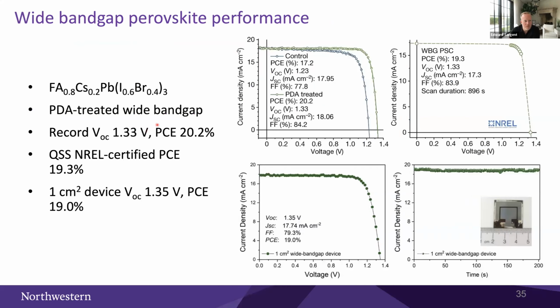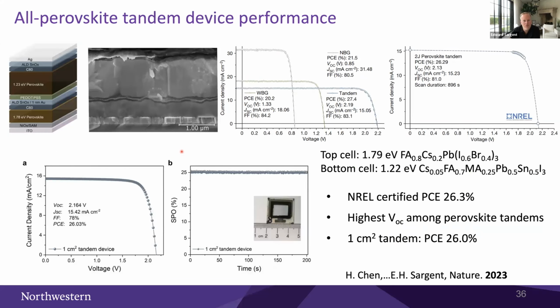In terms of performance, this led to an exciting VOC of 1.33 volts. Good progress for these single junction devices for the high bandgap layer in terms of the PCE, including an NREL certified 19.3% PCE, something that enabled us to integrate these to form tandems that had a 26.3% NREL certified PCE, something that was retained quite well as we scaled to a square centimeter.